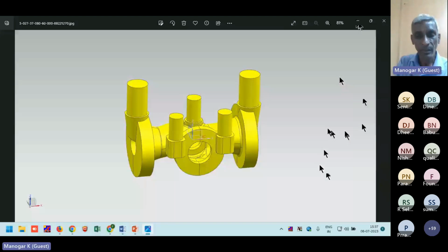Sir, that's what I explained to you. See, the exothermic sleeve will give 45%. That means it gives 4.5 kg of feed metal from this 10 kg riser. Okay. Insulating sleeve gives only 3.5 kg from the 10 kg riser. So then you have to consider that sleeve and the riser size, diameter or height accordingly. That you have to arrive at from your own cube test result and apply. Don't go as per the supplier recommendation. It is not practically meeting in many cases. Yes, even in simulation, we are failing. If you are playing the same thing, we should be careful in judiciously using the riser size and volume.